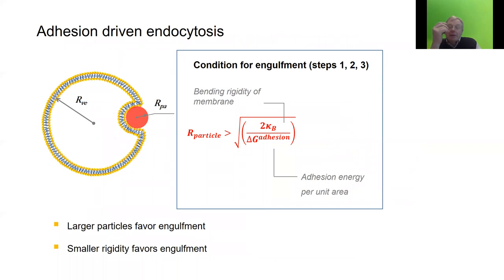Now let's look at that. Can we do this very easily? We can, because there is some very simple physics behind it. If you have a particle which adsorbs at the vesicle, the question whether the vesicle will start to wrap up the particle is determined by the strength of the adsorption energy. If it is large, the particle has a lot of power to deform the vesicle shape, and by the elasticity, the flexibility of the vesicle membrane.